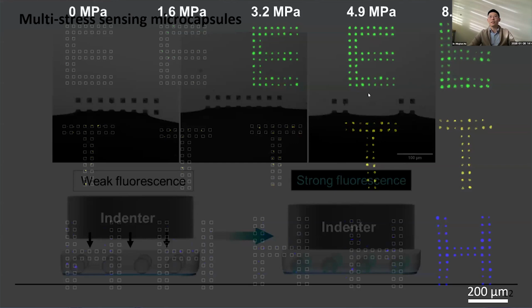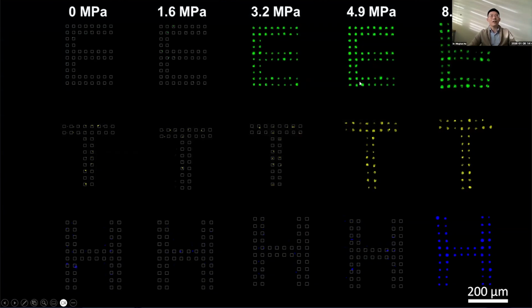And we did the test. This is what we got. As I show here, we can clearly see when we use the microcapsule with the smallest breaking force, it will be broken at the 3.2 megapascal stress. And when we have, for example, this yellow dye, it's encapsulated inside the microcapsule with the higher breaking force, and then it will have the higher breaking stress. And with that, we can prove that our microcapsules can nicely translate the mechanical breaking force into the optical signal.